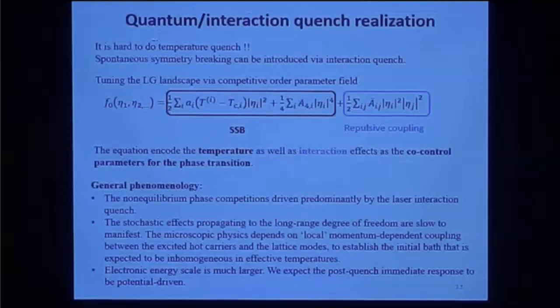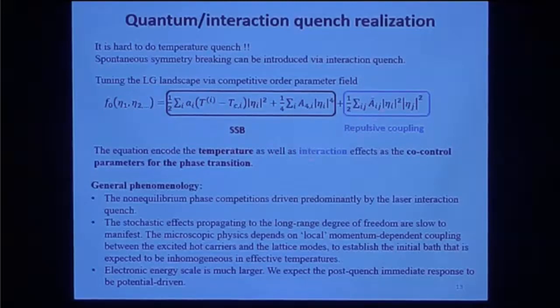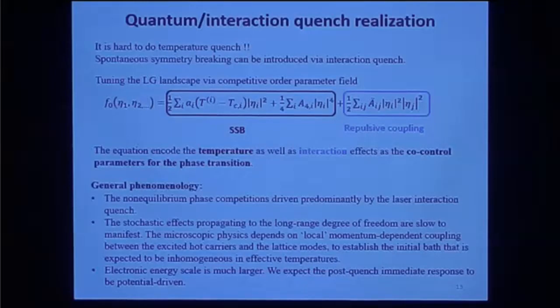We can write a Landau-Ginzburg equation to describe the phase transition. It has a temperature term giving the critical temperature of each state, and also an interaction term. If you change the interaction term, you don't need to change the temperature to drive the phase transition. For example, if you reduce the interaction term by suppressing the electronic order, you can rewrite the equation absorbing this term into the bracket — effectively changing the critical temperature without heating the system.